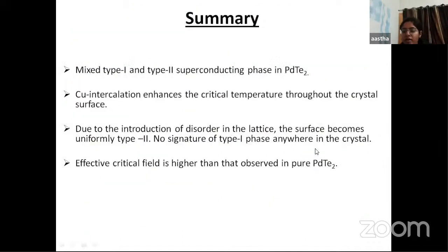So here I would like to conclude my talk. Initially, on bare PdTe2, we observed mixed type 1 and type 2 superconductivity. Upon the introduction of disorder, or upon intercalation of copper, the surface becomes uniformly type 2. We did not observe any signature of type 1 superconducting phase in the crystal. In addition to this homogeneous type 2, the critical temperature also gets enhanced, and the effective critical field was also observed to be higher than in pure PdTe2.